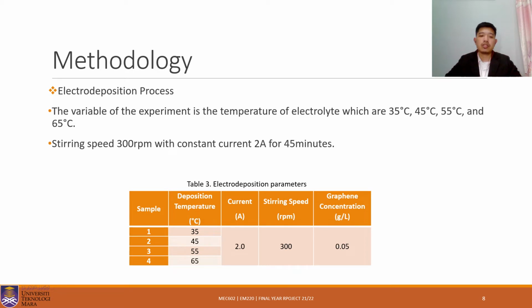After that, the electrodeposition process. The variable of the experiment is the temperature of the electrolyte, which are 35 degrees Celsius, 45 degrees Celsius, 55 degrees Celsius and 65 degrees Celsius. The stirring speed is 300 rpm with constant current 2 ampere for 45 minutes. Table 3 shows the electrodeposition parameters. Sample number 1 used 35 degrees Celsius, sample number 2 45 degrees Celsius, sample number 3 55 degrees Celsius and sample number 4 is 65 degrees Celsius.